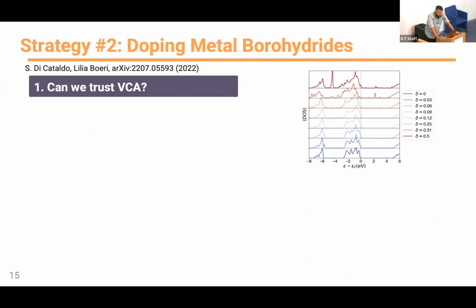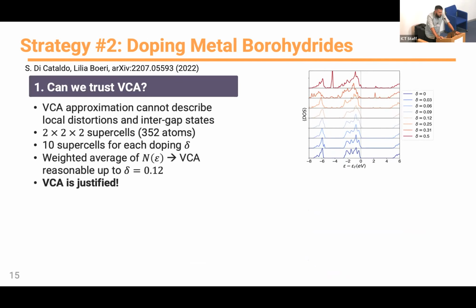So to check the trustworthiness of the virtual crystal approximation, what I did was essentially try to think of the limitation of the VCA, which is that it cannot describe local distortion, and it cannot describe intergap states due to distortion of the cell. So we constructed 2x2x2 supercells, and here we are talking about 352 atoms. And in each supercell, we randomly assigned the position of calcium 10 times, and we averaged the density of states.